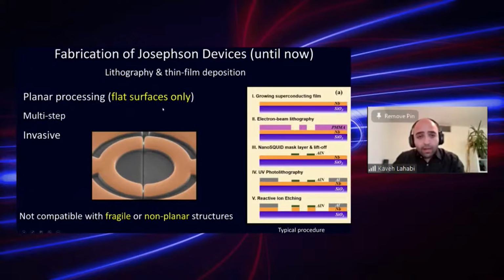You see, as I'm sure you're all aware, so far the fabrication of squids has solely relied on thin film deposition and lithography techniques. And this is, of course, a multi-step procedure, and it can be invasive. So you often need to dip your sample in solutions and bombard it with ions. But more importantly, this is only compatible with planar structures. So you need a flat substrate, which is not what I have in most cases.